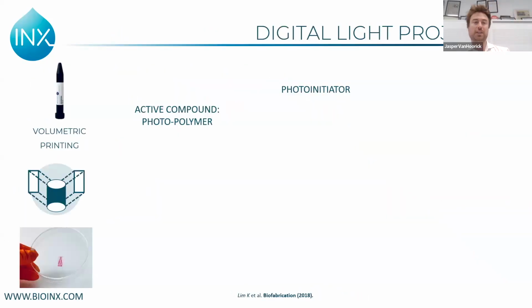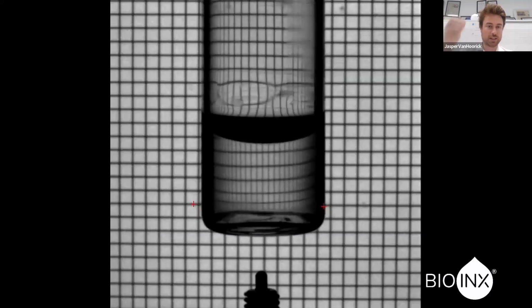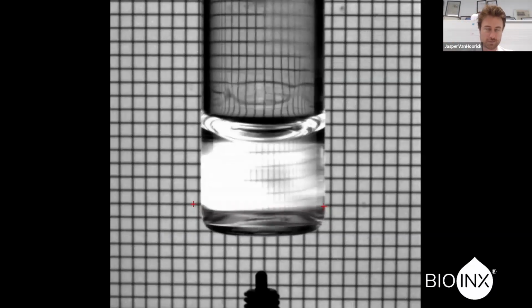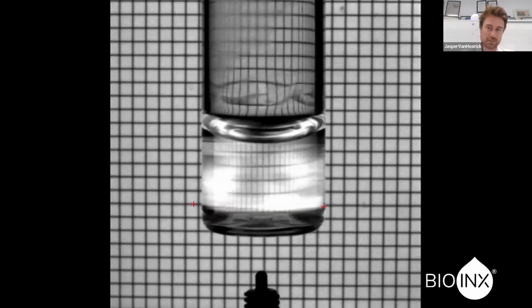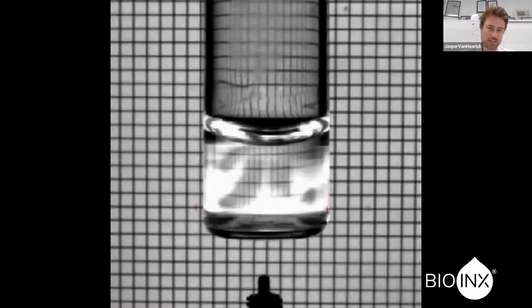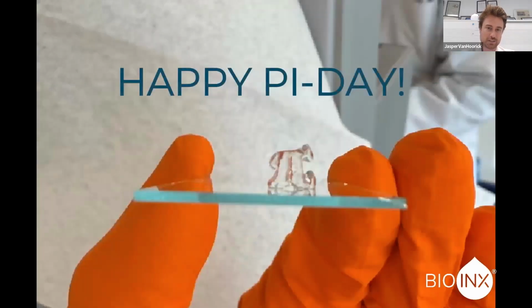Here on the formulation, you again have a photopolymer, a photoinitiator, and something which is added sometimes is a radical scavenger to increase the resolution. And with that, you can get a structure. This was, for example, something we did in our lab a few months ago for Pi Day. We printed this Pi letter in a gelatin-based resin. And as you can see, this is real time. It's about 30 seconds, I think. You can already see it appearing. Afterwards, you just dissolve the material and you get your structure.